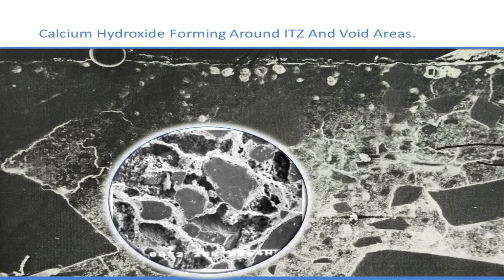As you can see in this picture, the inset inside the circle is a top view looking down at pool plaster. Those are grains of sand, and right around each grain of sand we have the ITZ — Interfacial Transition Zone — and they're all white. That white product is the calcium hydroxide. Calcium hydroxide fills in all these ITZs, these craze cracks, these fissures, these gaps. This is where calcium hydroxide lives. This is the very basic DNA of all cement products. We can't change that.